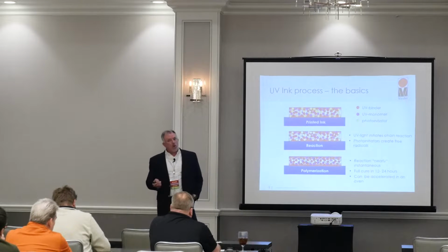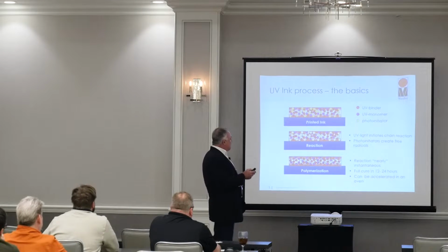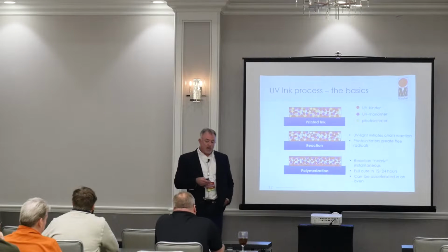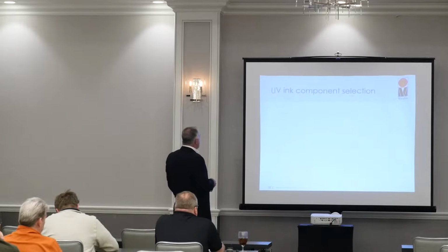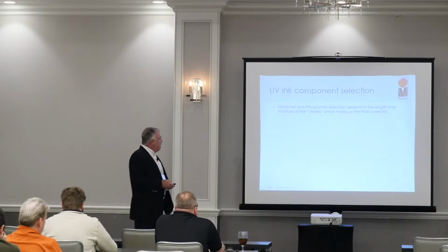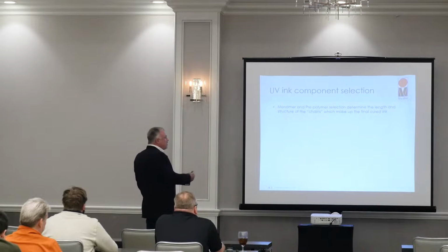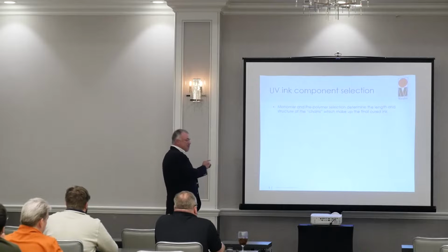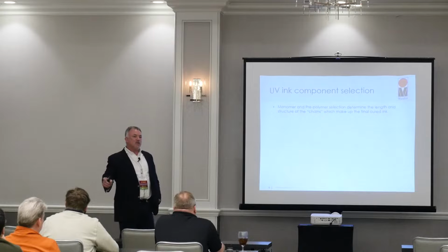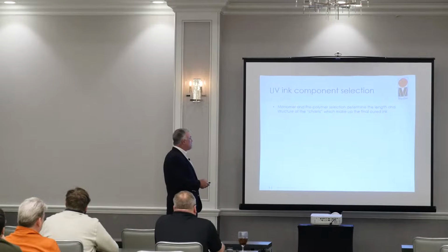And you have a full cure that's going to require up to 24 hours. So be aware that if you're going to test for durability or anything like that, give it at least 24 hours or put it in an oven. That will increase the speed of that reaction. So let's talk a little bit about UV ink and why it's different than most inks, like solvent inks, water-based inks, etc. It's because you have such a wide range of raw material that you can use. From the photo initiators to all the other elements, it's the selection of these items that allow you to tailor an ink to a very specific application, which is why requirements of the final product need to be mentioned at the very beginning of the process.